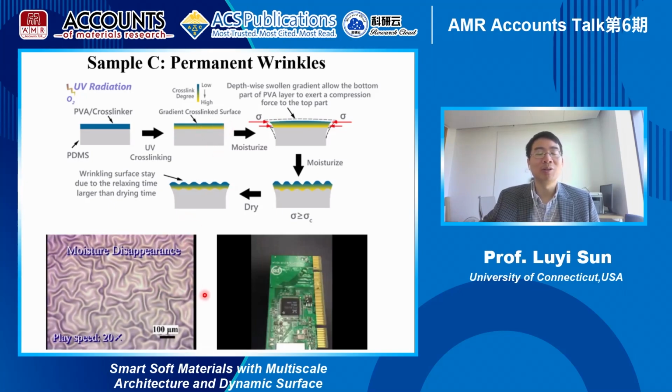Or someone may say, hey, you can possibly re-wet it. Well, you can re-wet it, but during the re-wetting process, it actually swells even more. Therefore, it will generate more wrinkles instead of fewer wrinkles. Because of that, the wrinkle will always stop at this stage.